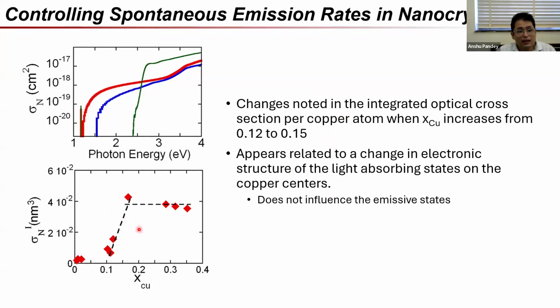But what is interesting is none of this change in its spectroscopy of absorption seems to interfere at all with the emission. So, emission is not being changed at all. And emission is still happening mainly from states which seem to be rather localized relative to each other.